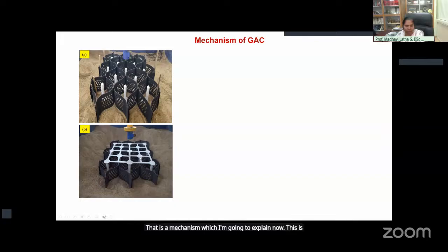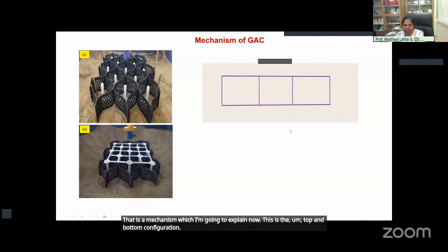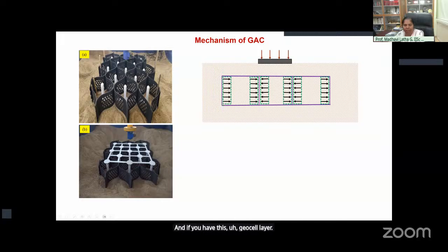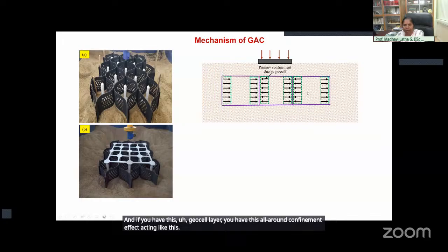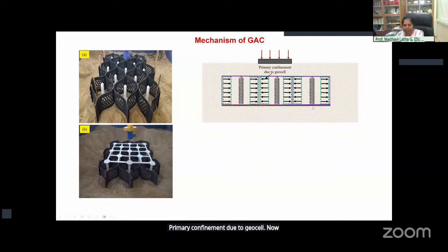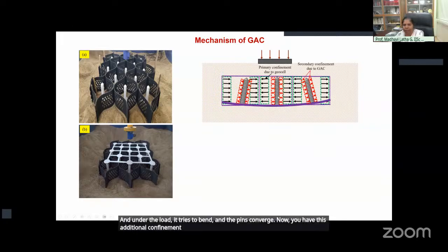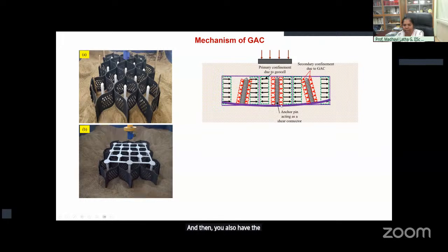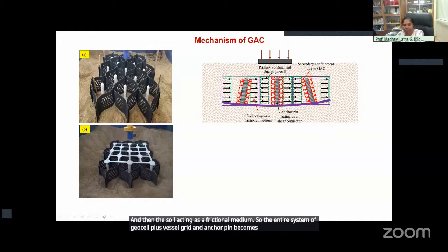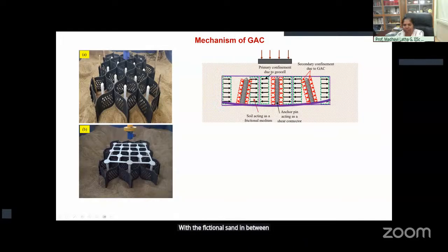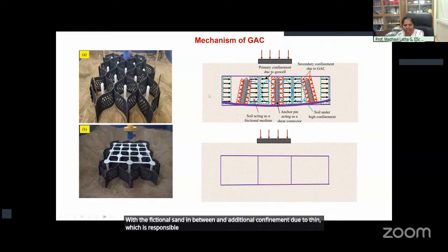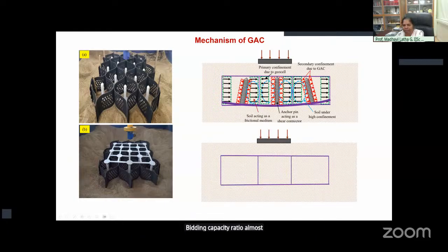This is the top and bottom configuration. And if you have this geocell layer, you have this all-round confinement effect acting like this: primary confinement due to the geocell. Now we have a basal geogrid with anchor pins, and under the load it tries to bend and the pins converge. Now you have this additional confinement effect due to the pin, and then you also have the anchor pin acting as a shear connector, and the soil acting as a frictional medium. So the entire system of geocell plus basal grid and anchor pin becomes one system with frictional sand in between and additional confinement due to the pin, which is responsible for this enhanced bearing capacity ratio, almost 3.5 times the original bearing capacity.